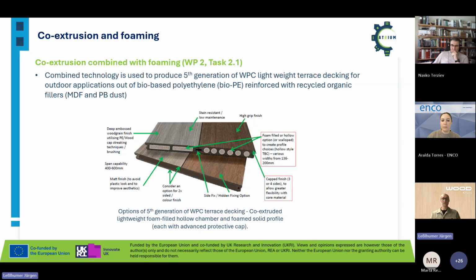And this technology we use to produce the so-called next or 5th generation of these WPC lightweight terrace decking for outdoor application. And as mentioned before, we use for the matrix bio-based polyethylene and reinforce this with recycled organic fillers from the furniture industry. So we use recycled fibers from medium density fiberboards and particle boards, and also mixtures of these two types of dust.